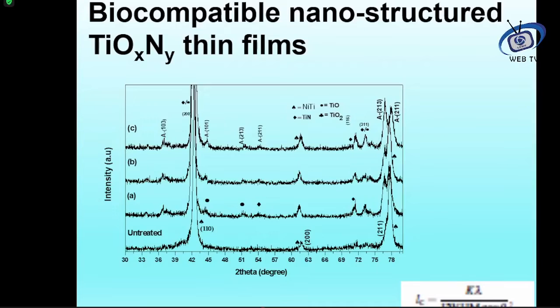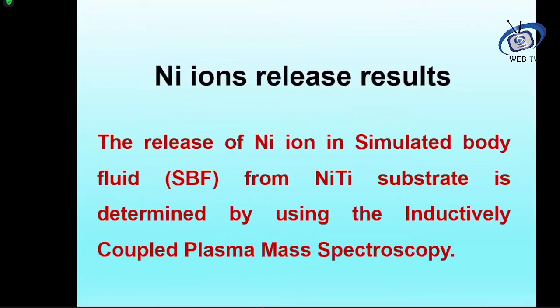We deposited a biomaterial film, which is the titanium oxynitride film. Here you can see the XRD pattern where we can see the nickel titanium, titanium oxide, and titanium nitride peaks. They are deposited at different oxygen flow rates. We developed a simulated body fluid, which is almost like the body fluid. Nickel ion release has been checked by placing our film in the SBF, or simulated body fluid.